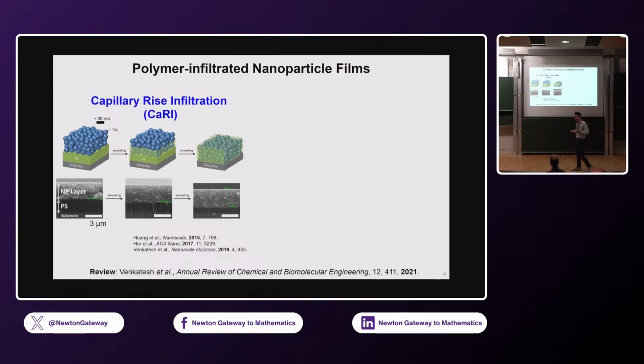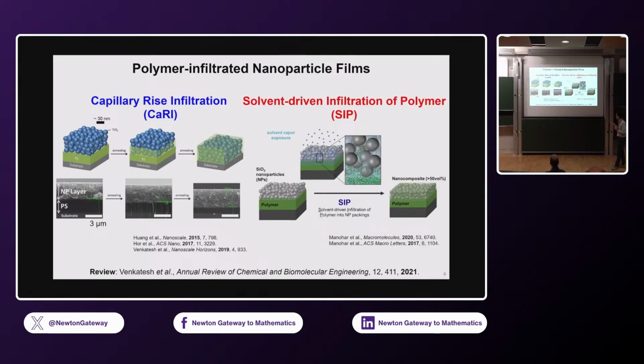The second way we can get there is, instead of using heat, some polymers degrade before they become fluidized. So we expose this bilayer to a solvent vapor rich environment. What happens in such a case is that the solvent vapor undergoes something known as capillary condensation. So it condenses within the particle packing. If the solvent is a good solvent, this solvent now diffuses into the polymer, and now the polymers are able to infiltrate into the solvent-filled pores. And once you've removed the solvent, you again end up with these very, very highly loaded nanocomposite materials.